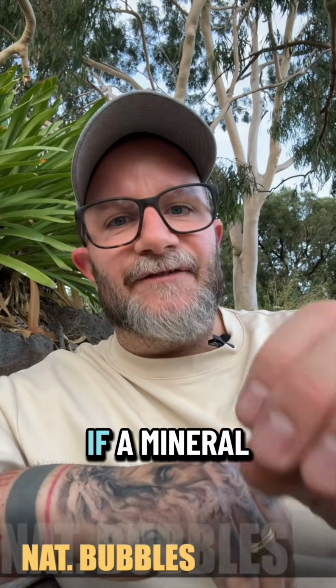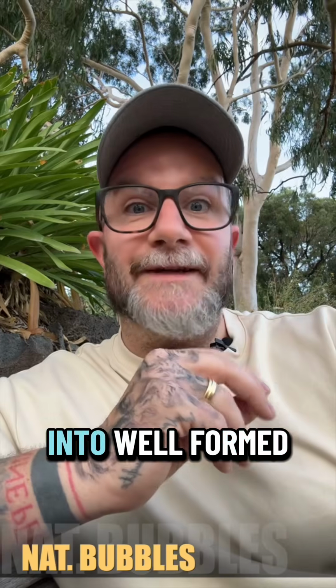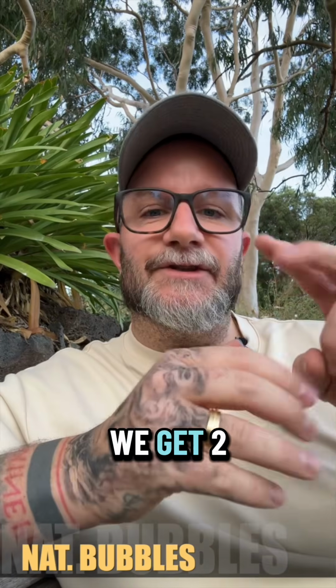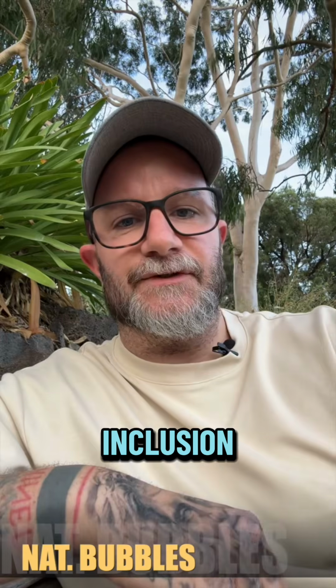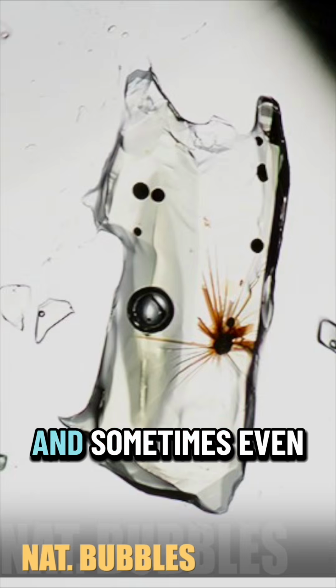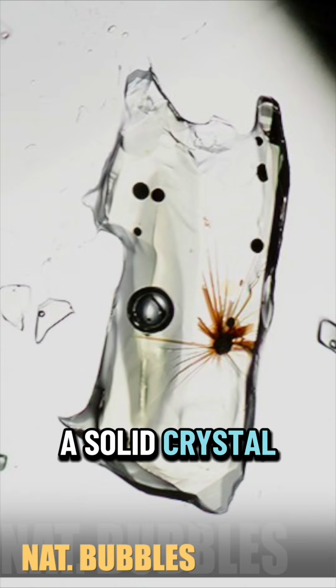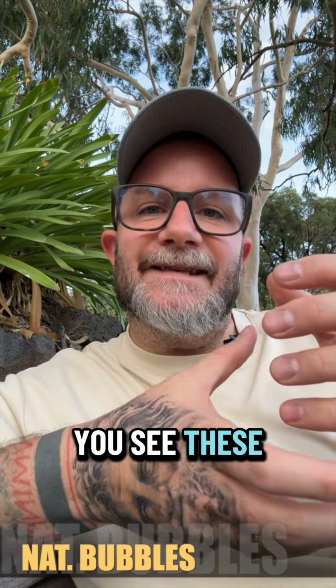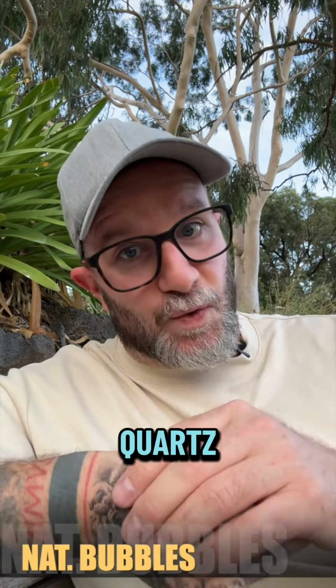However, if a mineral has the proper time to grow into well-formed crystals, we get two-phase or three-phase inclusions. We are talking about a little pocket of liquid with a gas bubble and sometimes even a solid crystal trapped inside. You'll see these a lot in natural emeralds and quartz.